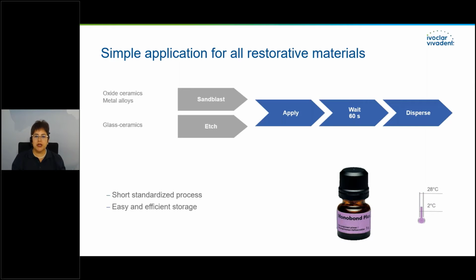To say it in another way, oxide ceramic and metal alloys always need to be sandblasted. Glass ceramics, we etch with hydrofluoric acid, and depending on the glass ceramic, this could be 60 or 20 seconds. And finally, afterwards, we can apply Monobond Plus, always for 60 seconds. We wait the 60 seconds, and then we just disperse it with air. So it is a short, standardized process.